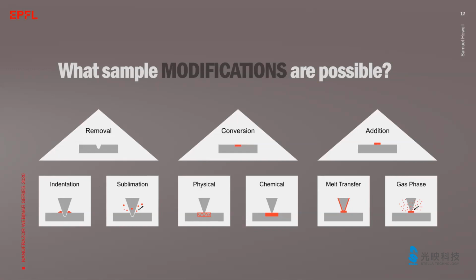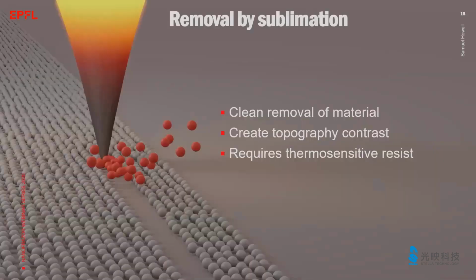So let's first look at the removal by sublimation. In this process, material is sublimated from the substrate by local heating with the tip. For nanofabrication, it's important that the material is removed from the substrate without leaving residues or redeposition near the patterns. The aim is to create a topography contrast which can then be transferred into a useful material such as silicon or silicon oxide. And sublimation can be achieved with specifically thermosensitive resists.